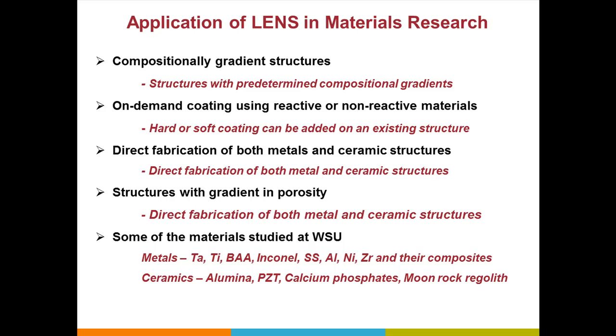For a metal like tantalum, it absorbs laser like crazy - so much that in conventional processing, tantalum is very difficult because of such a high melting point. In lens, when you hit it with the laser, it's like water. So we can build tantalum parts even at fairly low laser power, 400 watts or less, without any problem. In fact, sometimes it vaporizes, it absorbs so much - because it absorbs the laser and it's a poor conductor.